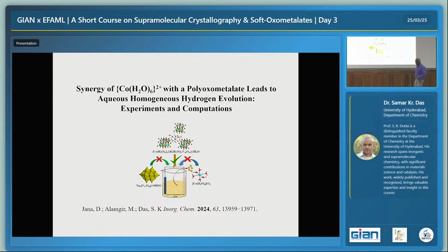Why? When you solve the crystal structure, we found a very interesting hydrogen bonding network between this cobalt aqua and decavanadate. Not only that, we took the mass spectrum of that, and the same mass is getting maintained. Whatever species we find, we got the same mass. We believe that the compound in the solid state, when we dissolve in water, remains the same hydrogen bonded structure. That is why a synergy gets established, and this gives continuous water oxidation.